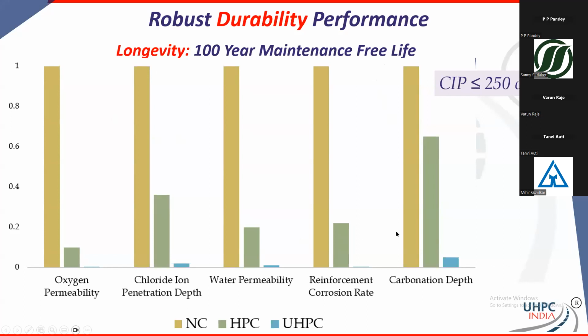And if you can still see some blue, that's down below over here. No oxygen permeability, hardly anything. Carbonation depth is lower. Other permeabilities, chloride ion penetration depth, etc., all lower. RCPT values are typically lower than 250 coulombs, anywhere in the range of 50, 100, 150, something like that, but typically lower than 250 coulombs. Any day, this material is much, much, much more durable than both concrete and steel, I would say.